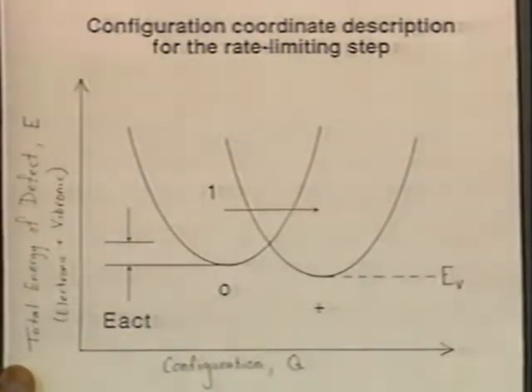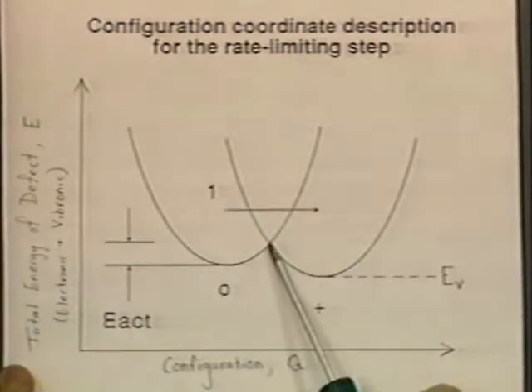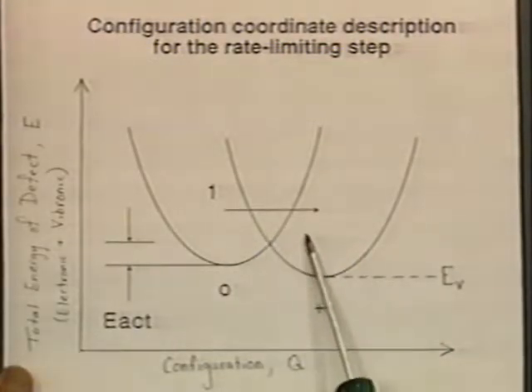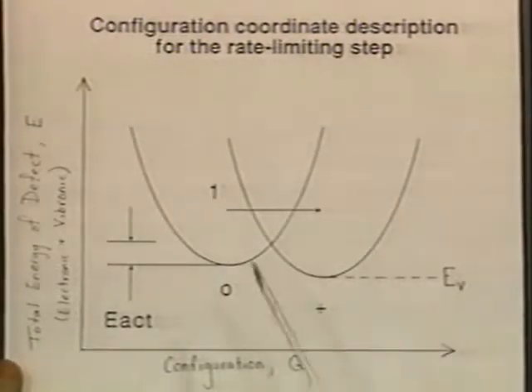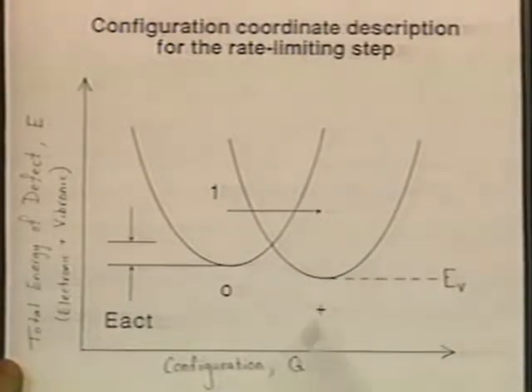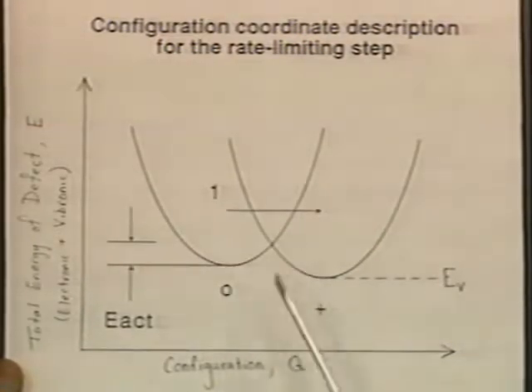Now, the way you think about transitions is you are vibrating in this configuration. If you have enough energy to make it to this point, you don't know what configuration you're in. You can make the transition depending on probability issues. So you make this transition down to this state here. And if you make this transition, if this is a lower energy, a particular temperature isn't enough to allow you to go back into this state. It's kind of an irreversible process, at least at the temperature that you're looking at.